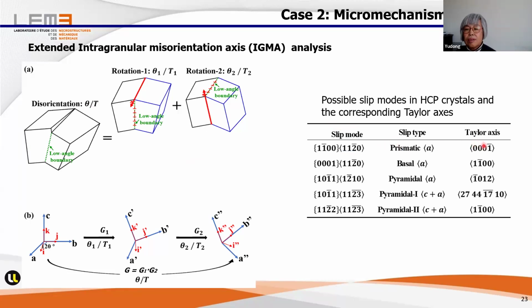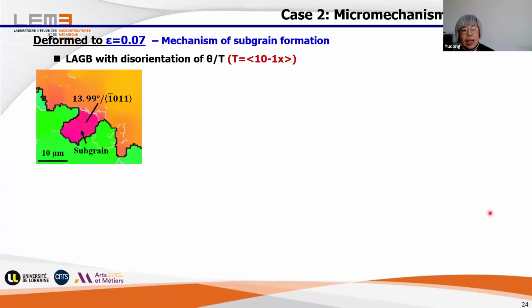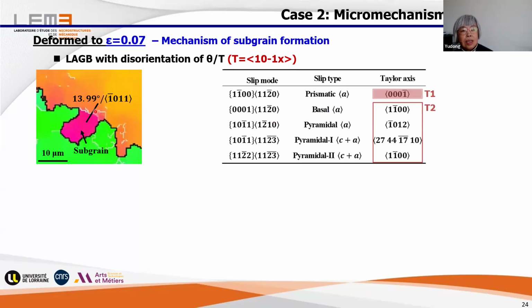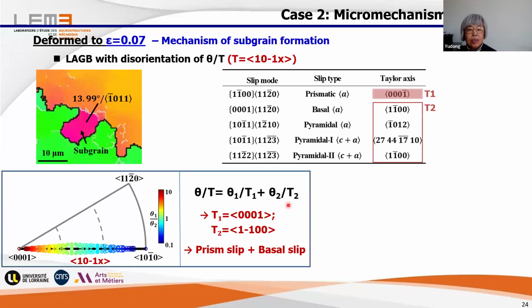How did Fengming do it? For the first rotation, she used the prismatic slip, and for the second rotation, she introduced all the possible slips. Here is an example. We see here we have a bulging and a boundary closing this bulged part. And then she made the simulation. You see, we fix the two axes and just vary the angles, and then calculate the general axis and angle.